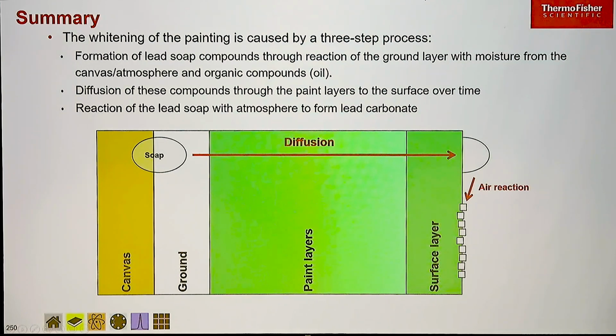They're able to protect the painting, keep it in an inert atmosphere so that it doesn't get worse, and clean the surface so that they can prevent the build-up of these bubbles and stop the painting changing any further. So there is a kind of happy ending to the story. But yes, that's how, in a very odd occurrence, XPS can be used to preserve artworks. And that's the only time I've ever heard it being used for that. But it's still my favourite application example for XPS.